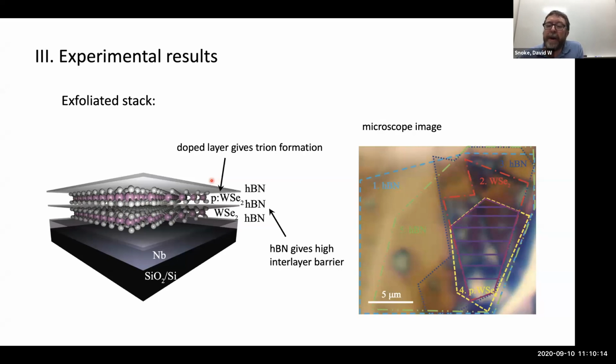Okay, so let me just run through the experiments. Metal, HBN insulator, then the tungsten diselenide, another HBN, another monolayer, this one p-doped, and then a top capping layer of HBN. And here you can see an actual photograph in which all these layers were stacked up. We did not put contacts on any of this yet. We're just doing spectroscopy, although we've started to work on trying to put an in-plane electric field on these things, but I don't have anything to report from that.